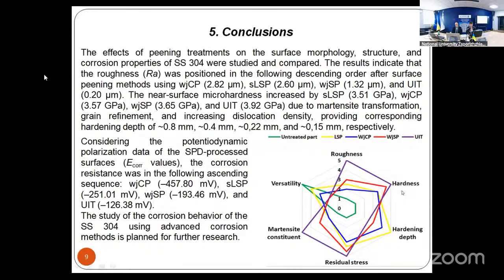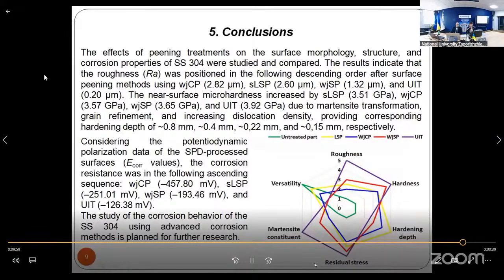the laser, cavitation and wet shot peening treatments can be recommended for surface finishing of complexly shaped or small size austenitic stainless steel parts, while the multi-pin ultrasonic treatment would be applicable for surface finishing of large size components with simple geometry.